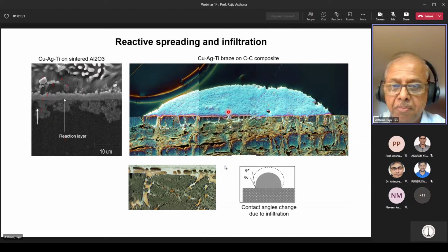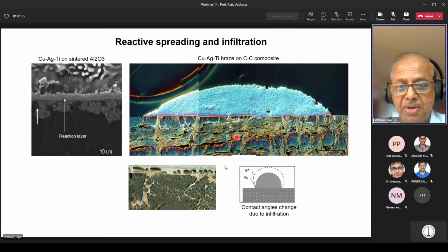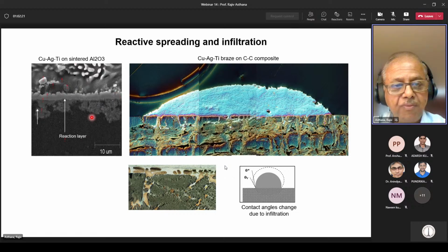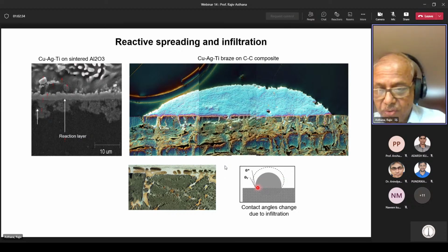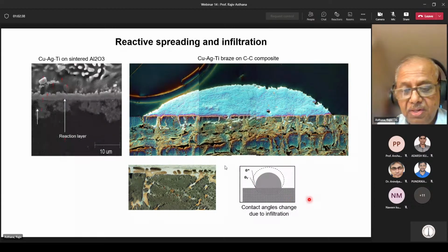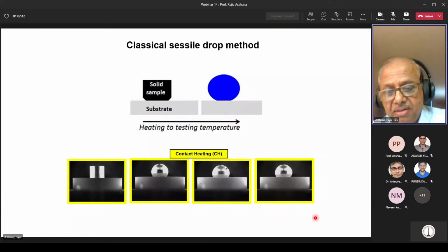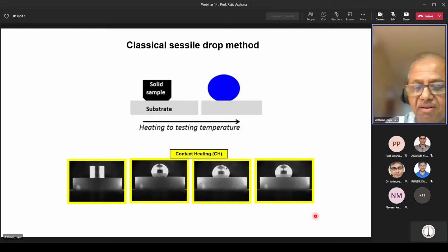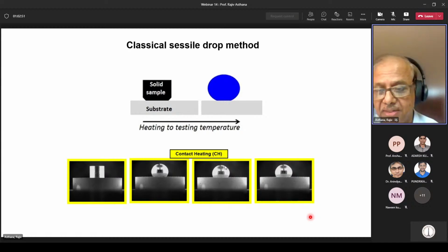Here you're looking at liquid copper, silver, titanium droplet on a carbon-carbon substrate. And we did some wetting test on carbon-carbon, and we saw obviously a lot of liquid being lost by penetration of the porous surface. Even in sintered aluminum oxide substrate, we see reaction layers forming between copper, silver, titanium braze and the substrate. So this is the reaction layer, but we also see some infiltration of the substrate. So in all these cases, the volume of the liquid is continuously changing because of infiltration and reaction, and that is going to change the angle of contact that you measure. So in many cases, the measured angle in high temperature systems is not really a thermodynamic angle. It is more of a practical indicator.